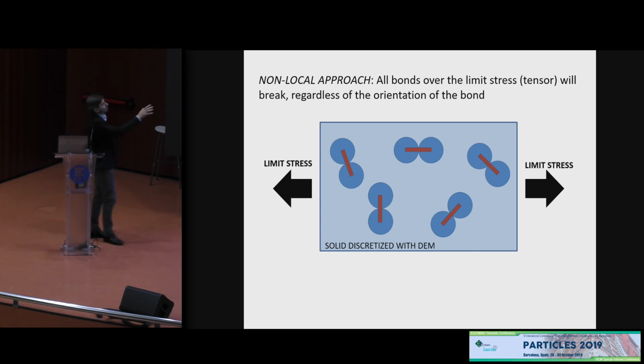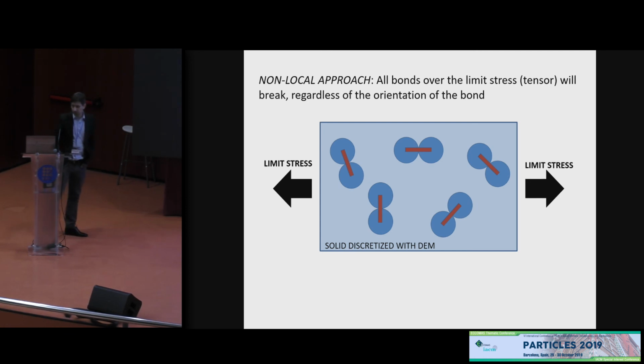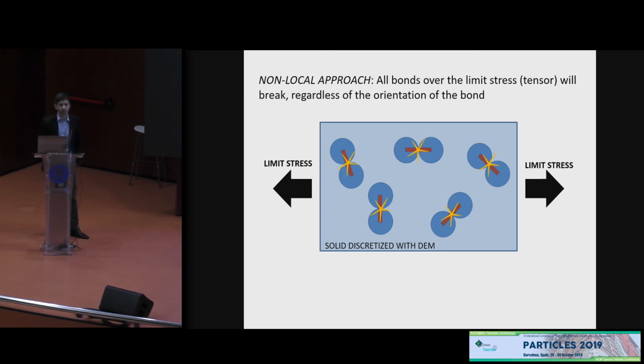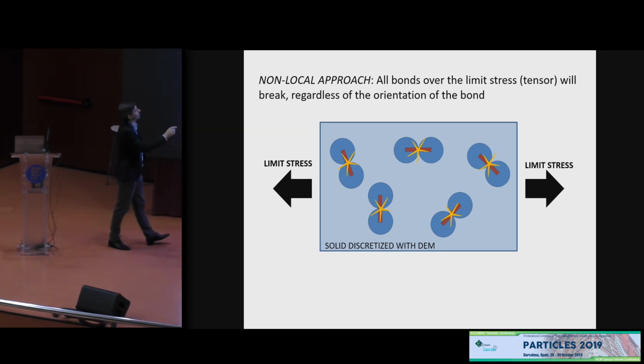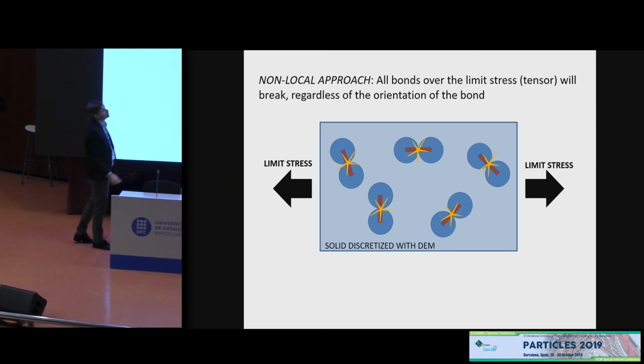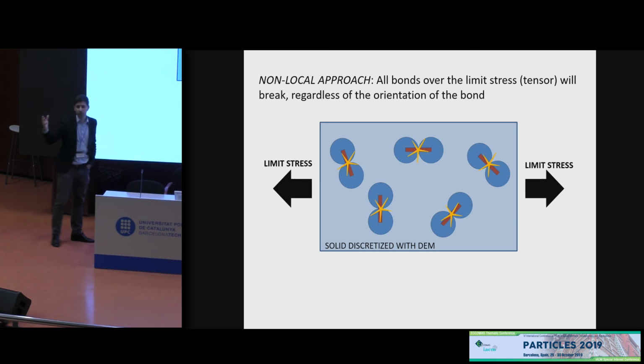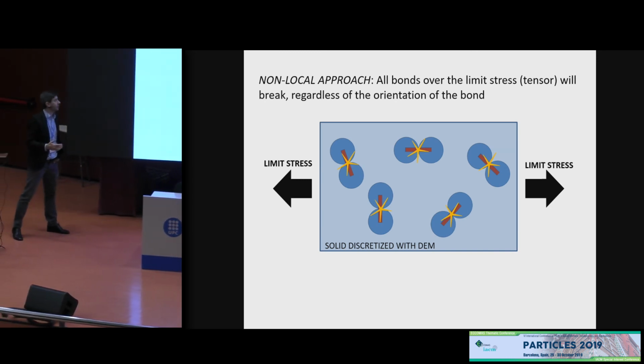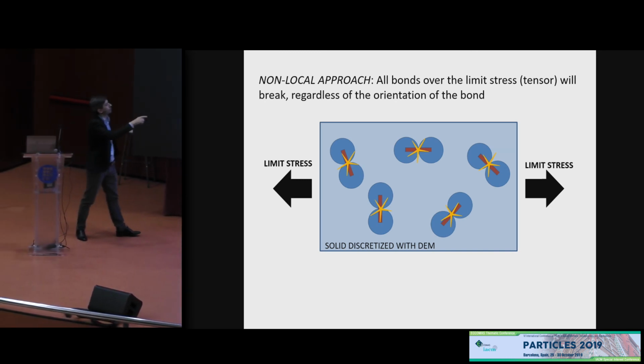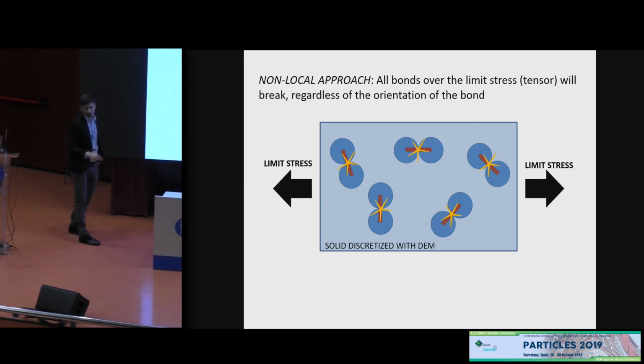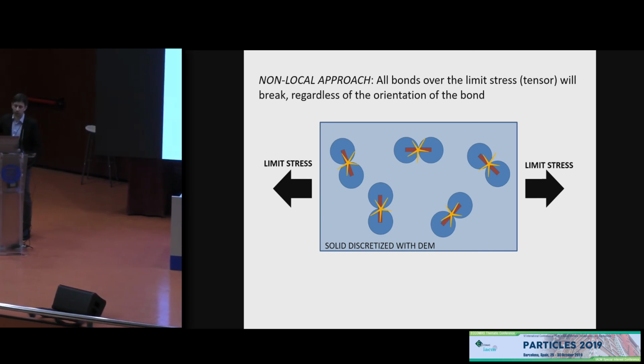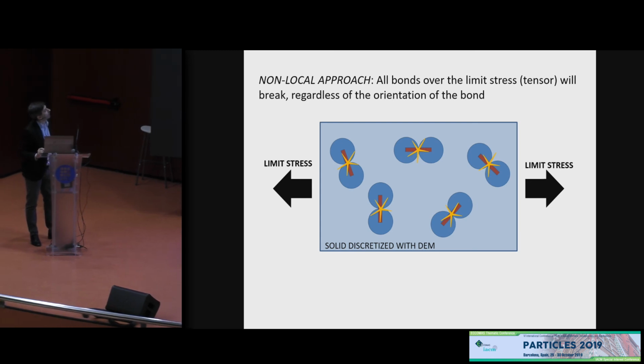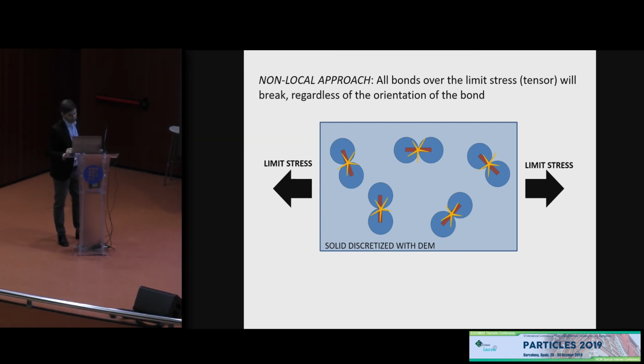if you put the solid under limit stress, all bonds should break at the same time, regardless of the orientation of the bond. We said at the beginning that orientation was important when you're using local stresses, so the information along the bond. But here, in this case, you're using the stress tensor, which doesn't care about the orientation of the bond. So all of them, apart from the heterogeneity that could appear, can break at the same time.